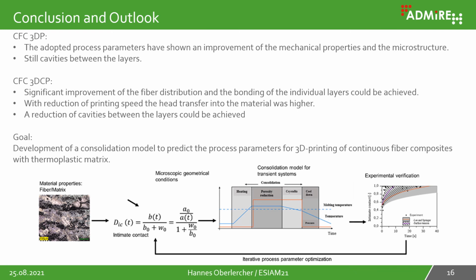Let's come to the conclusion and the outlook. With the Markforged 3D printing system, with adapted process parameters, we have shown that we can achieve an improvement of the mechanical properties and of the microstructure, but cavities still appear between the layers, and this reduces the mechanical properties. With the 3D consolidation printing system, we had a significant improvement of the fiber distribution and the bonding of the individual layers. With the reduction of the printing speed, the heat transfer into the material was much higher, and this leads to a reduction of the cavities between the layers.